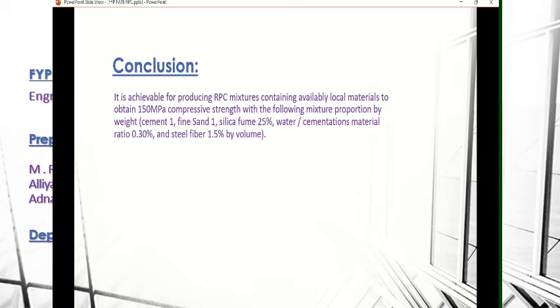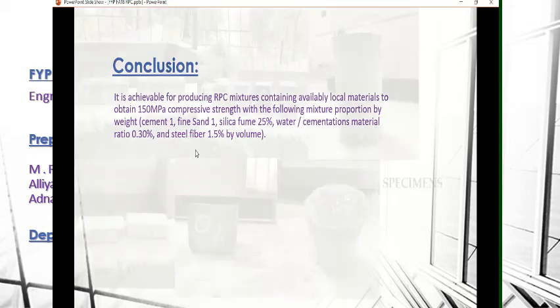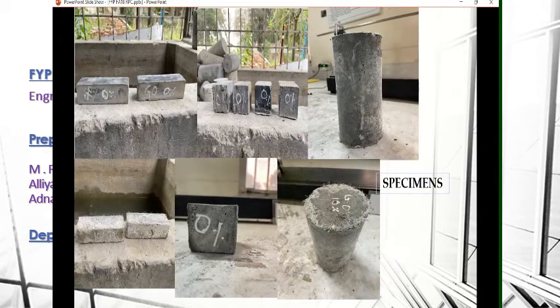cement 1%, fine sand 1%, silica fume 25% of volume, water cementitious material ratio 0.30, and steel fibers 1.5% by volume. So we have achieved the desired strength, which is much more than the structures made with ordinary concrete, which is in daily life use. So these are some pictures of the specimens we have cast and tested, from where we have drawn the results. Thank you.